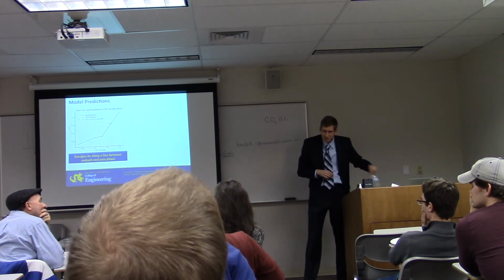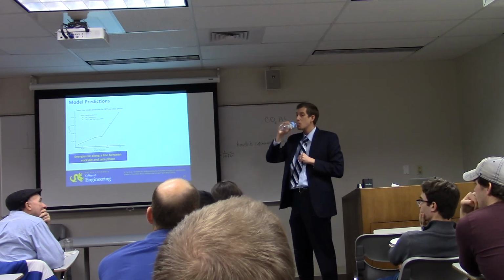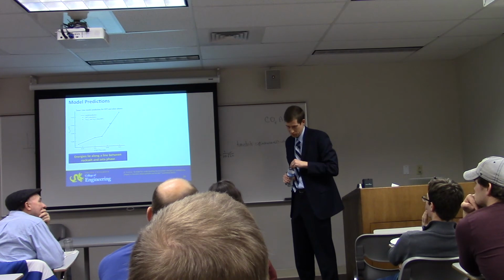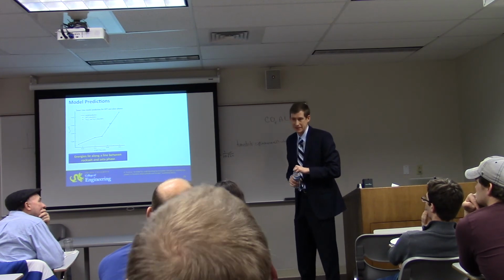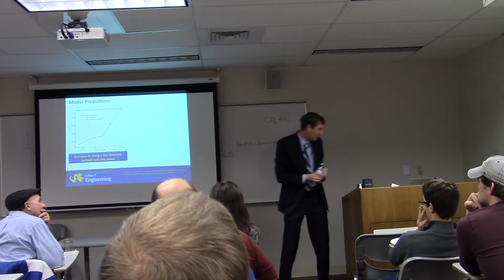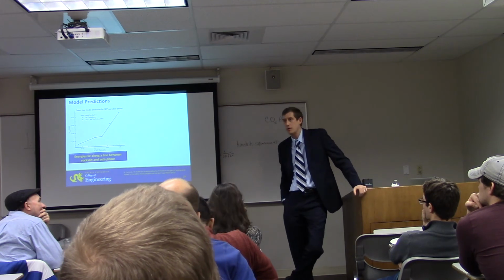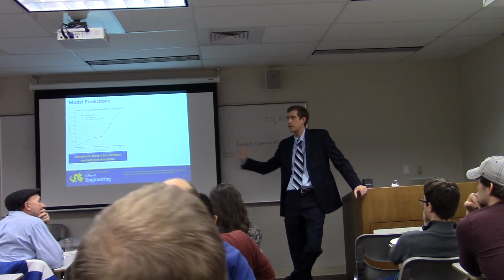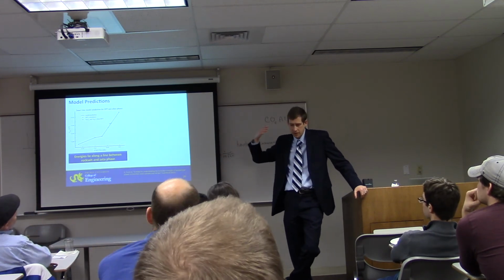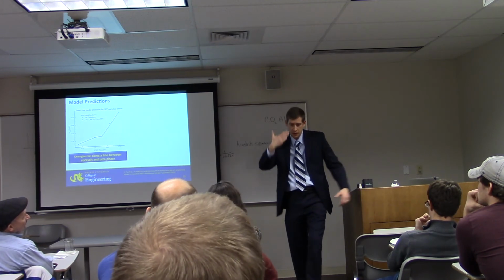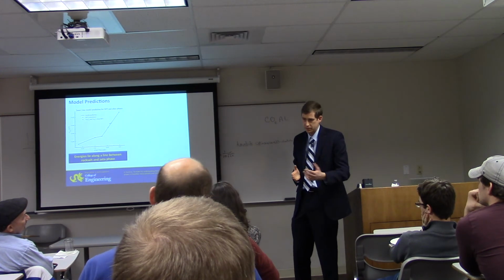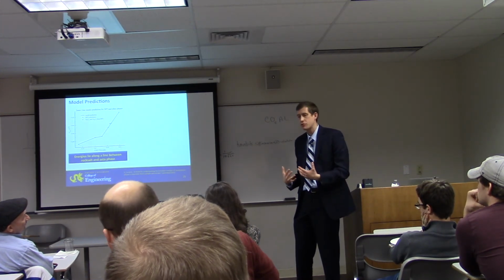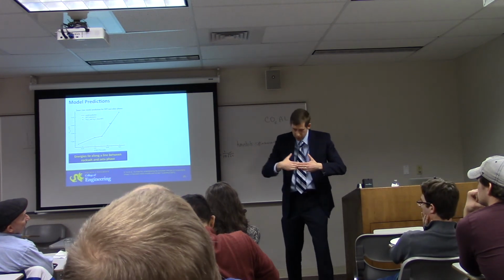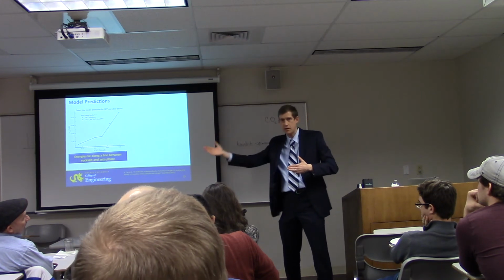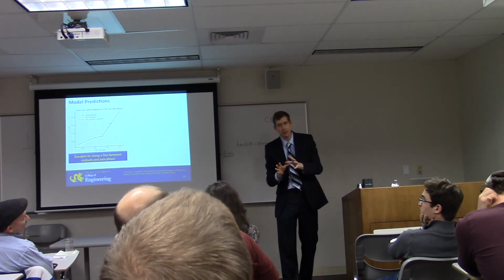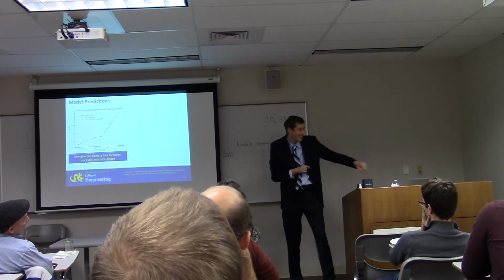Yeah. So I was intrigued by a comment you made early on about the zeta phase and that some people have measured a rising R curve for it. Mm-hmm. All I've seen is the abstract. We just discovered the paper like three days ago. And I know who the group is. They're the other group doing similar work. We've also done experimental work looking at the fracture toughness via indentation mechanics. I'm looking at what happens when you take a new indenter and come in at different angles relative to the laths. And you can see a very interesting phenomenon: you get cracking parallel to the laths, but perpendicular to them, you get a very serrated feature. But I wish I could answer more about the rising R curve. I've got to read that paper.